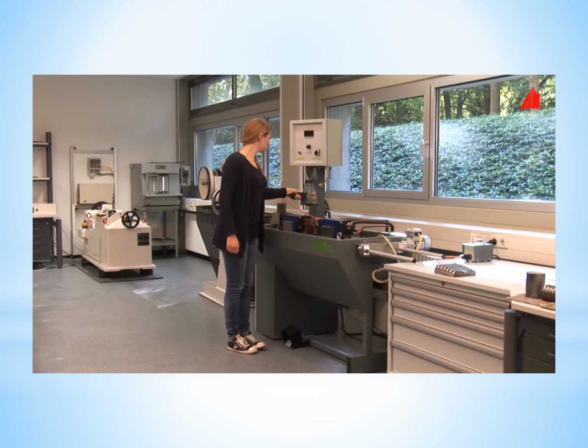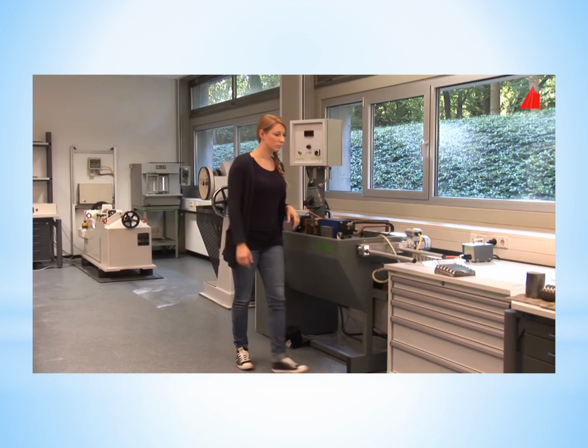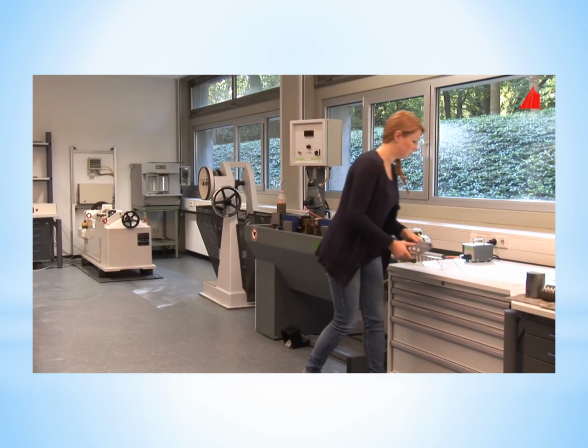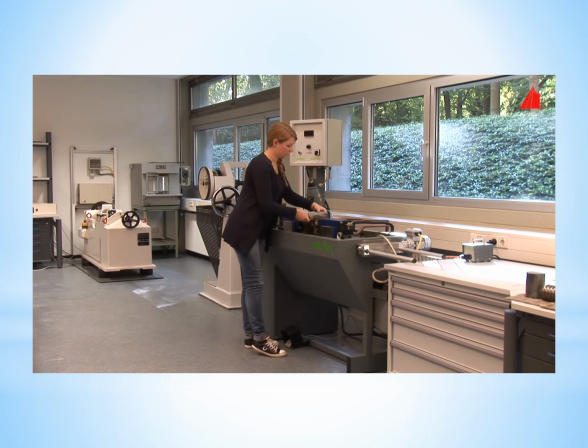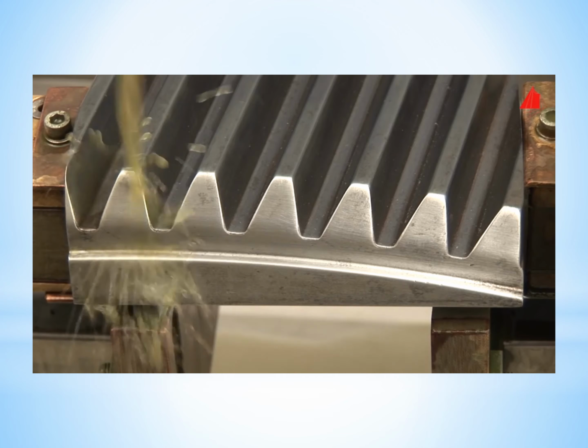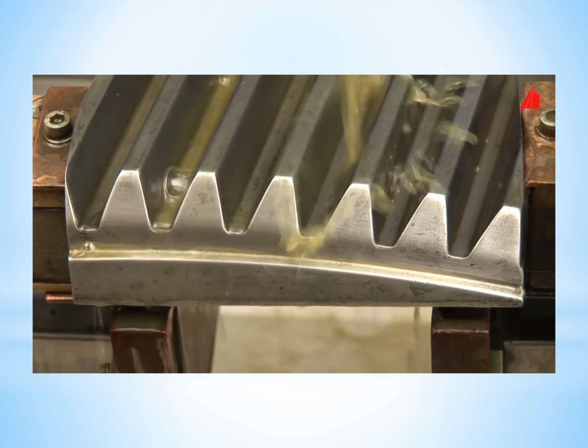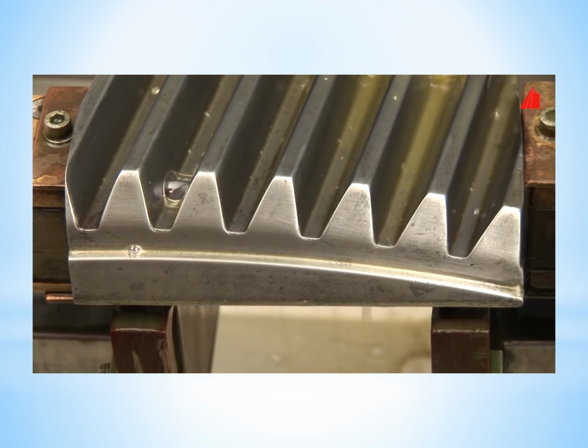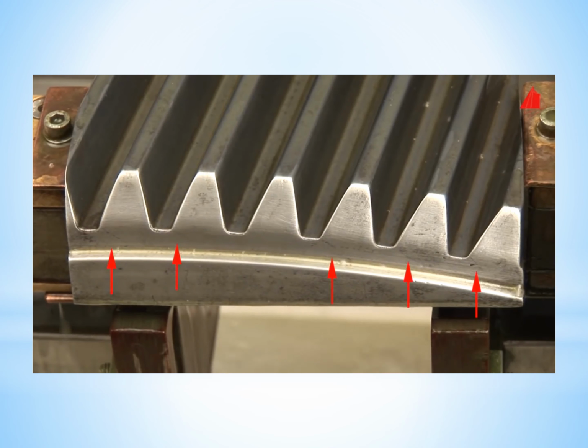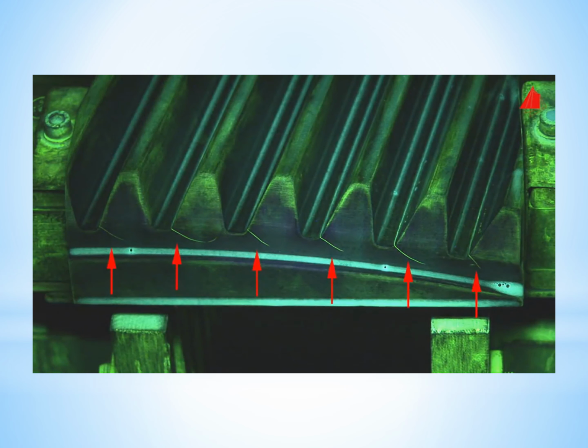Still another test piece has to face the magnetic particle inspection, a section of a large gear wheel. The same procedure again. Placing the gear wheel between the magnetic pole pieces, magnetizing and applying magnetic particle suspension. Already in daylight, there are indications of cracks, and again, they are best visible under ultraviolet light while darkening the daylight. The visible cracks are so-called fatigue cracks. They have been generated during the operation of the gear drive, due to a mismatch of the gear wheels.